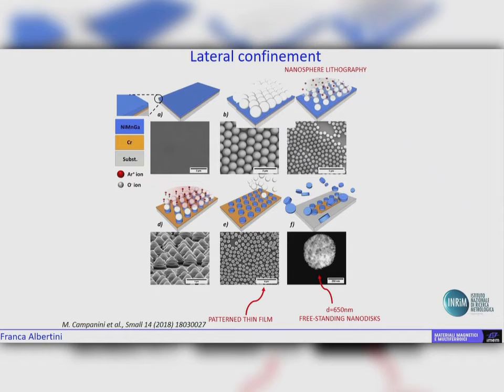As last slides, I show you the patterned film. In this case, we have obtained the patterning of these materials in collaboration with the Institute of Metrology of Turin in the group of Paola Tiberto, and we have exploited nanosphere lithography, and that is the self-assembling of nanospheres of two different sizes.